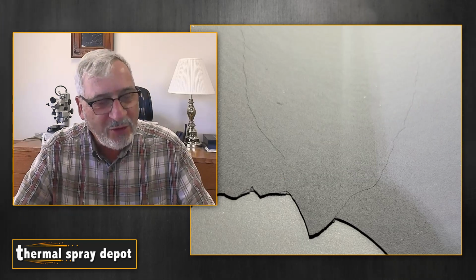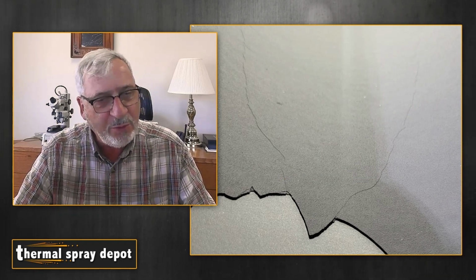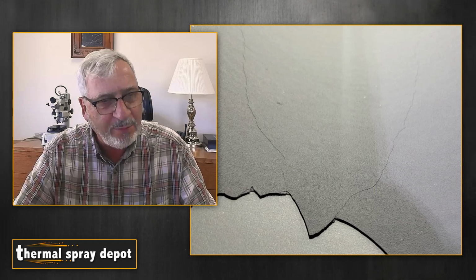But this is with thermal spray failure. So anyway, it actually spalled and it cracked. In this particular case, I believe this was a carbide coating. And you can see that the surface it was sprayed on looks pretty smooth. And that's where our inherent problem was: there was a surface prep problem on this one also.